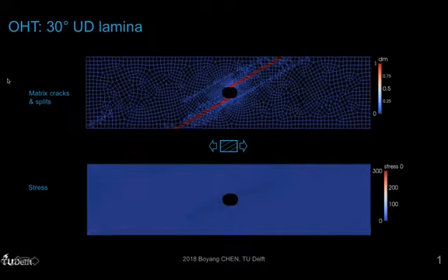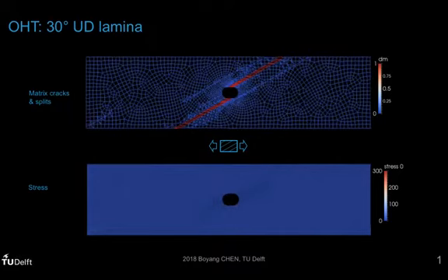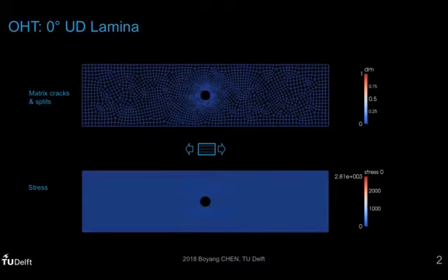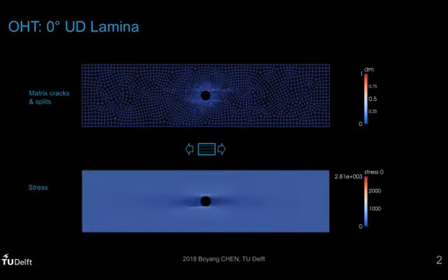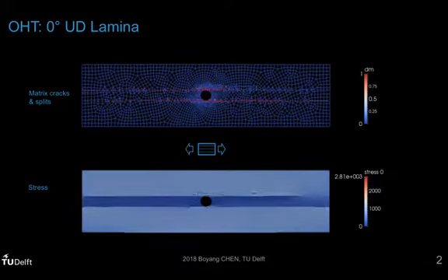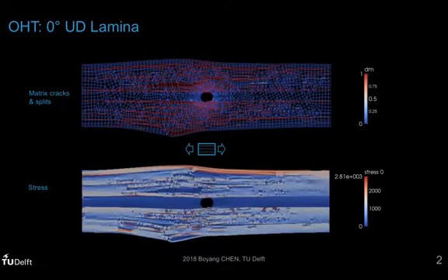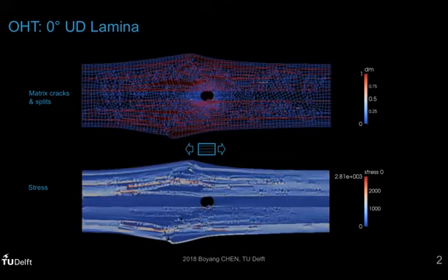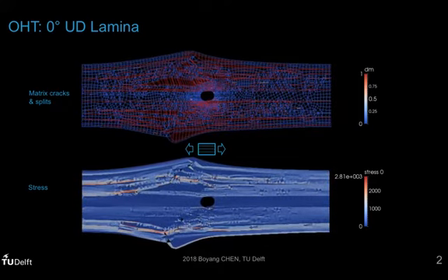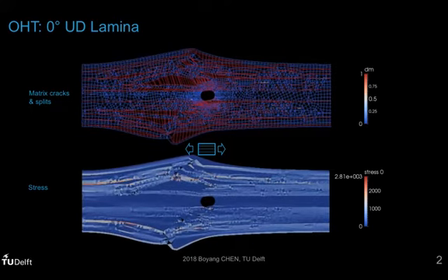And then on the very same mesh, if we just change to a different layup, this is the same mesh, and now it's a 0 degree. What we can see is that on the 0 degree ply, the mechanism changes completely. We have a longitudinal splitting. Then some of these panels would have a very quick, very sudden propagation of cracks, and you could see this kind of branching cracks. This typically happens in experiments in the 0 degree ply.